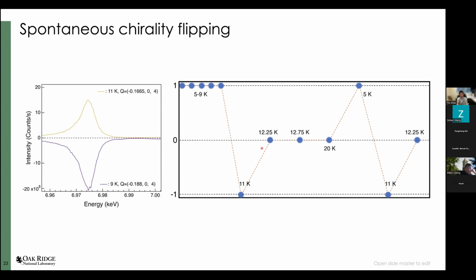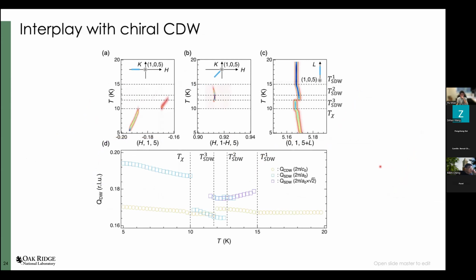We start changing temperature even above all the magnetic transition temperatures and cool back down. What happens is the chirality always remains the same. Even when we warm up above all the magnetic transition temperatures, that means there's a pinning center that exists above all the magnetic transition temperatures. So we ask ourselves why it happens. A naive expectation is that because there's a higher temperature CDW, maybe the CDW gives the pinning center. In that case, we expect the CDW to be strongly coupled with the SDW. Indeed, this is the case.